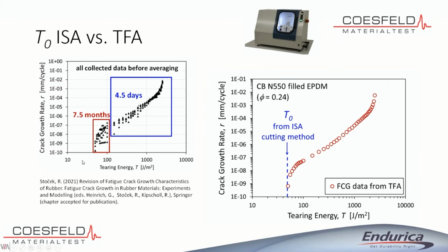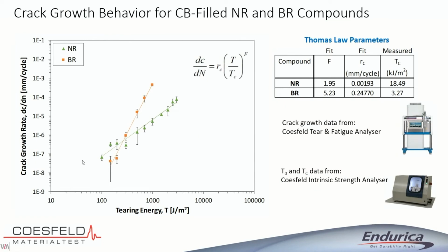We basically compared the threshold that we estimate with this method with the threshold that we measure with the ISA. And in fact, the comparison is very, very good. Different by, in this case, happened to be less than 5%. So, very, very strong correlation. Anyhow, that's the ISA method.